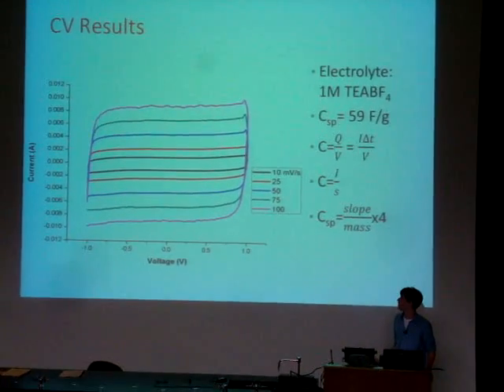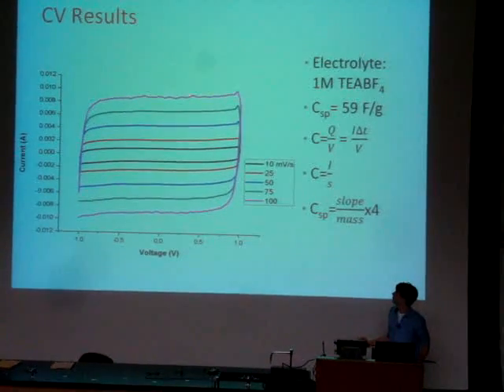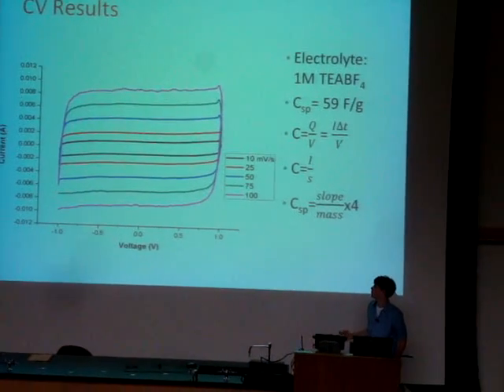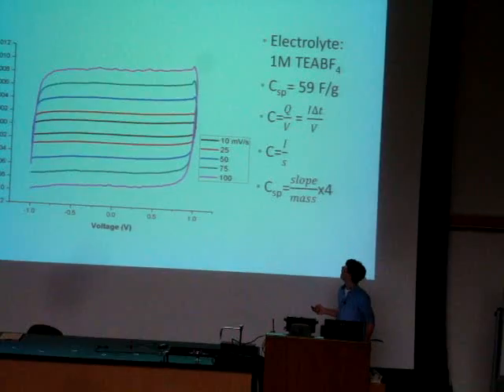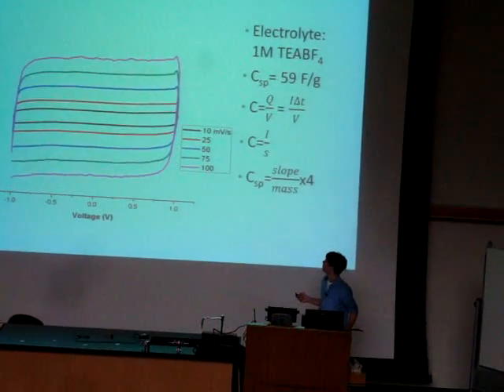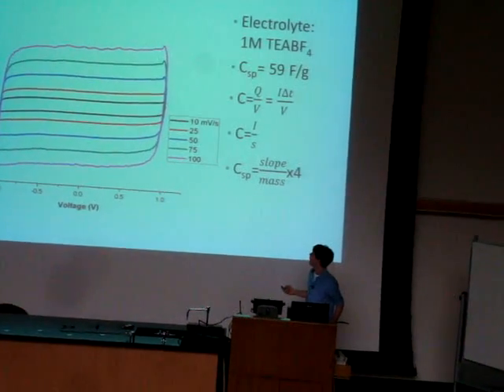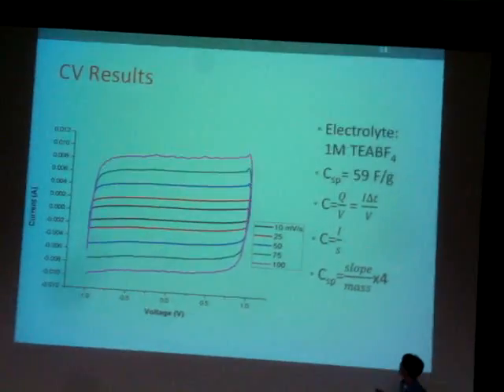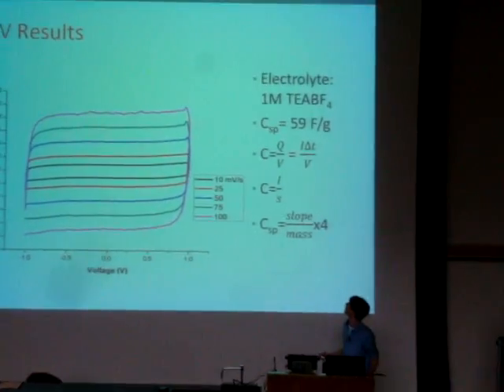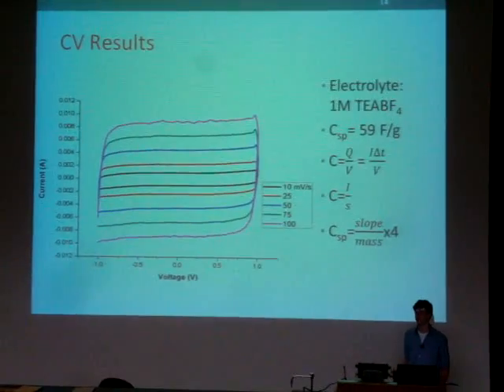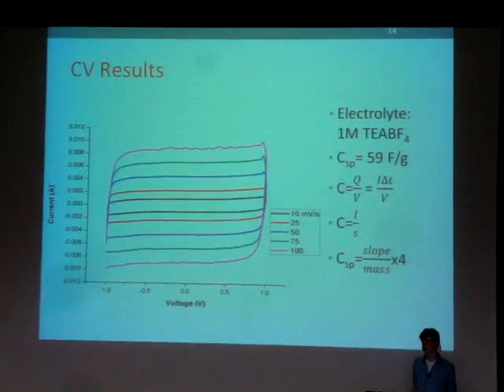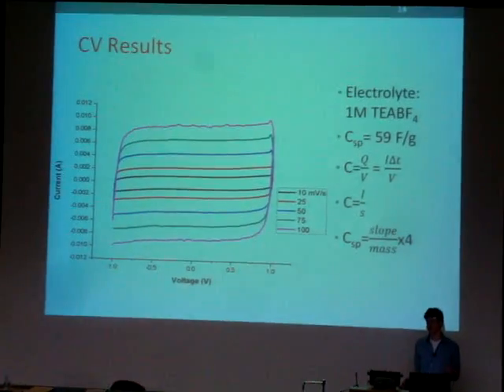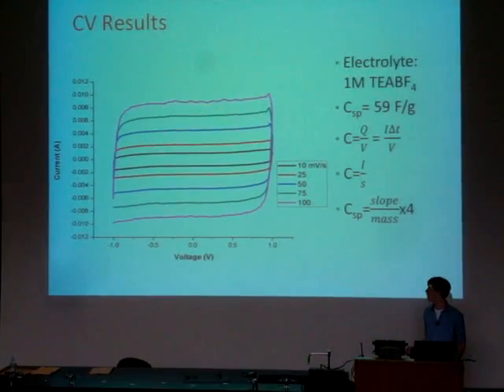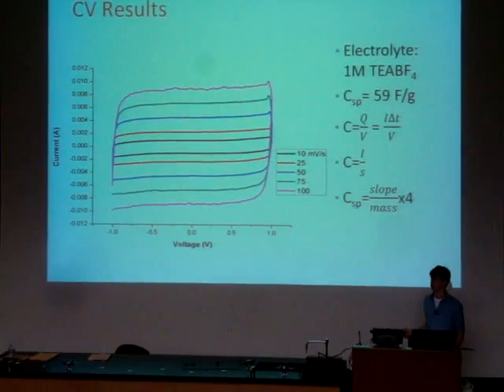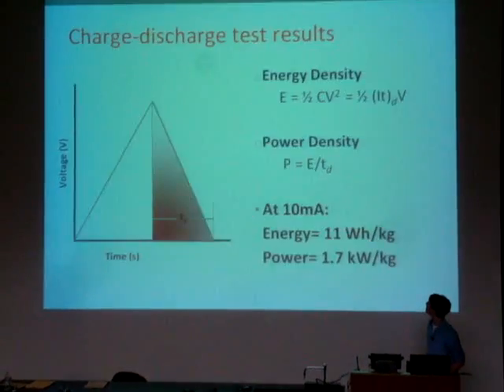The results we had were quite good considering the graph. It's very flat and box-like, which is indicative of an electric double layer. And we ended up graphing the current versus scan rate in order to get the slope, as seen here. Then we used these other equations from that graph in order to determine the specific capacitance. We got a specific capacitance of 59 farads per gram, which is really good considering that carbon nanotubes deposited just on SpectraCarb end up having a capacitance of only 3 farads per gram.